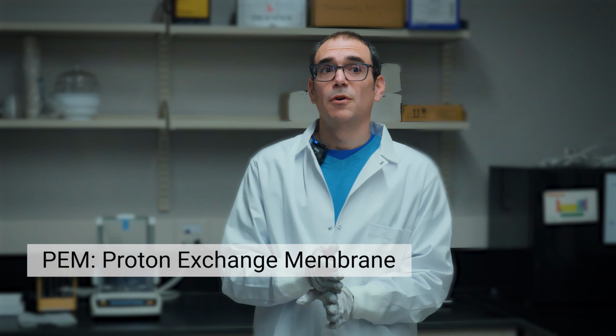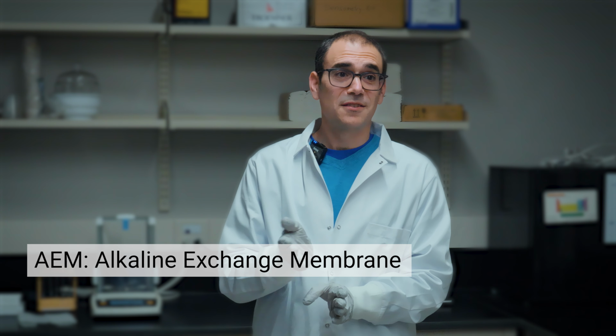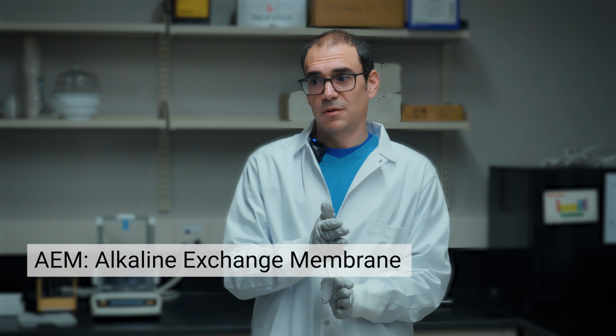So the main materials that you need to consider when you're looking at an electrolyzer is the membrane, which would be, again, PEM, meaning proton exchange membrane, or alkaline exchange membrane. And so for PEM, the material is Nafion and is very well studied. Alkaline exchange membranes are actually quite recent. Only in the last decade they've been stable enough to be able to make an electrolyzer. So that's one thing, and there is a big difference. PEM is very stable, very durable. AEMs are better for the environment, but they tend to not be as stable yet, and they require some fine-tuning of the reactants.